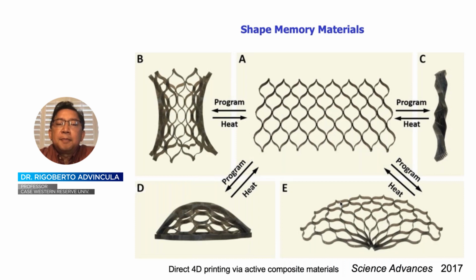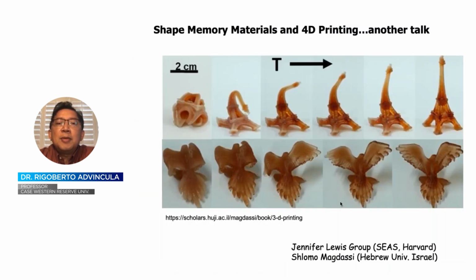And this might as well be a very good explanation or example of what we call 4D printing using composite materials. Okay. Or in the case of this photopolymerized material, so you have the Eiffel Tower and this dove, and you can have the initial shape, which is actually at a higher temperature, but as you fold or squeeze them, and then you apply the appropriate temperature, you can make them change shape or go back to another previous shape. So this shape memory material property is essentially 4D printing because the property is hidden when you first print the object, but then the application of the appropriate stimuli unlocks the other property that was originally present during 4D printing.